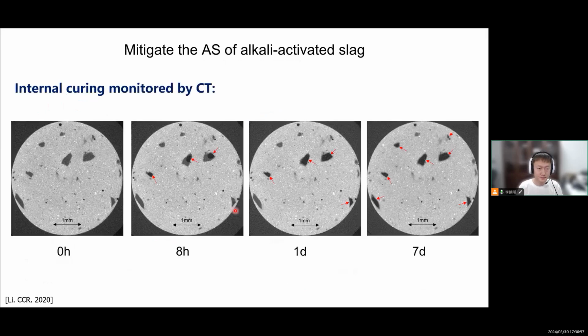And another way we tried to monitor this internal curing is by CT scan. So we can see in the beginning it is kind of gray, which indicates the liquid in the SAP, and then it tends to become black because all the liquid is released, and then there are air bubbles. And with the elapse of time, there are more black areas inside, which clearly shows how the liquid is going from the inside of SAP to outside.